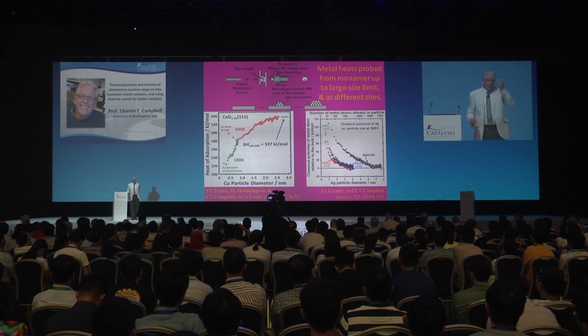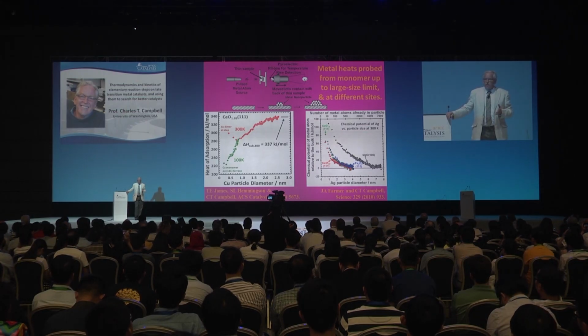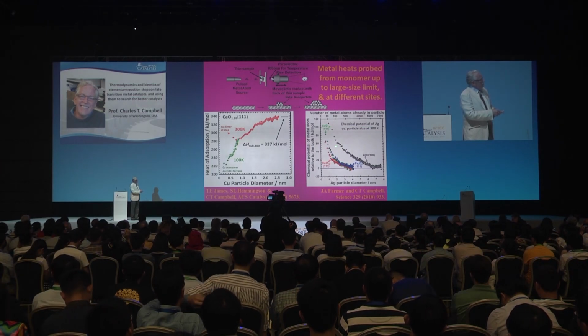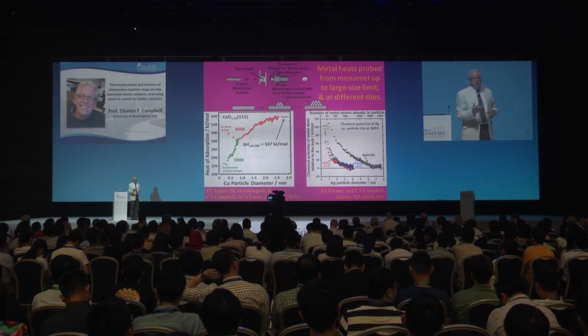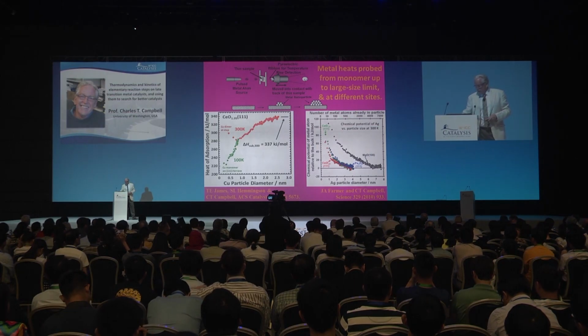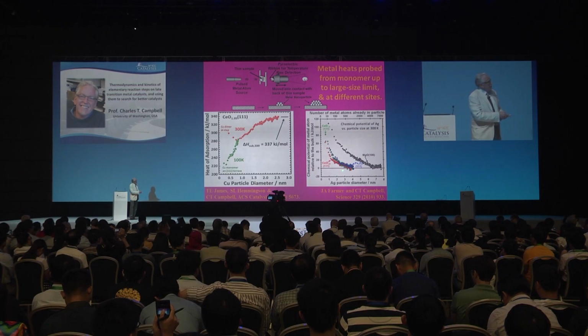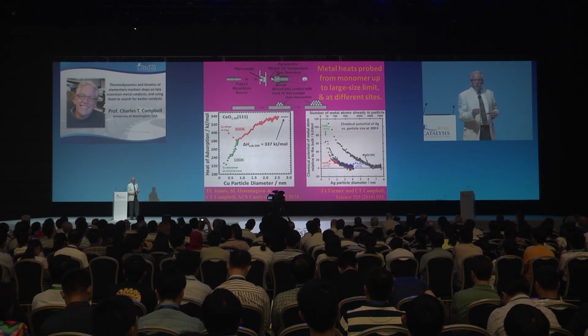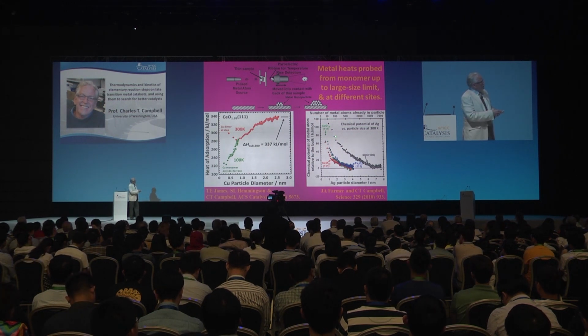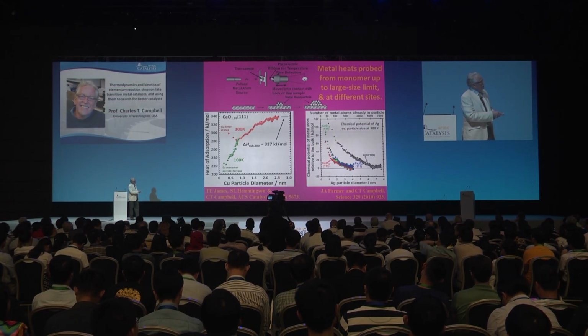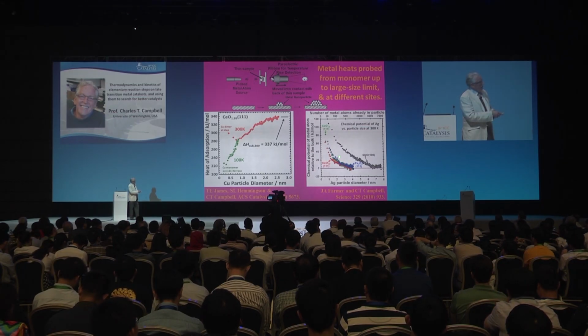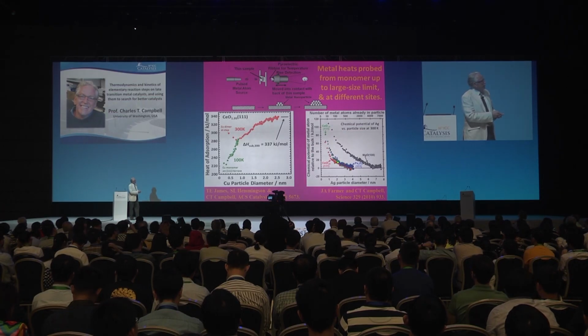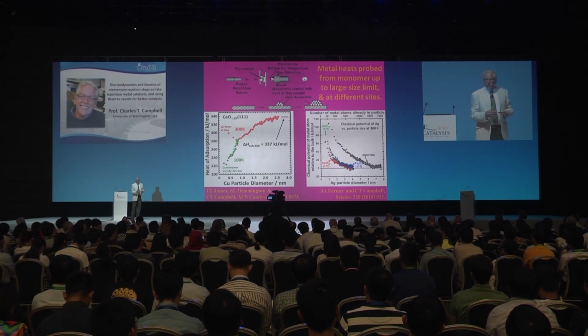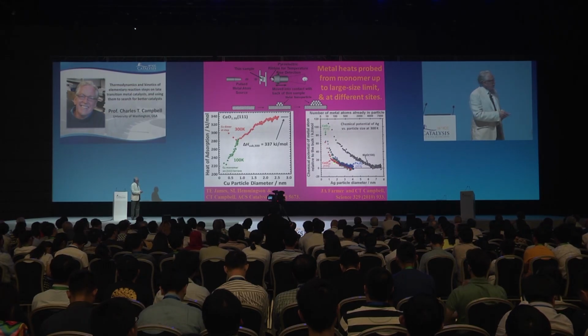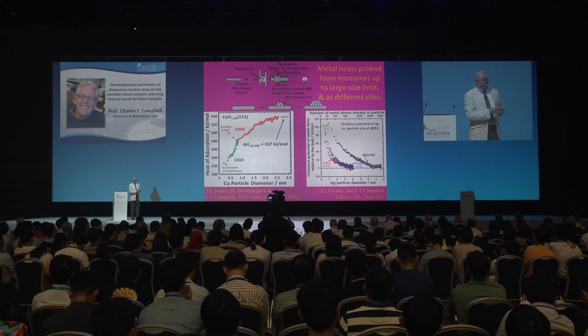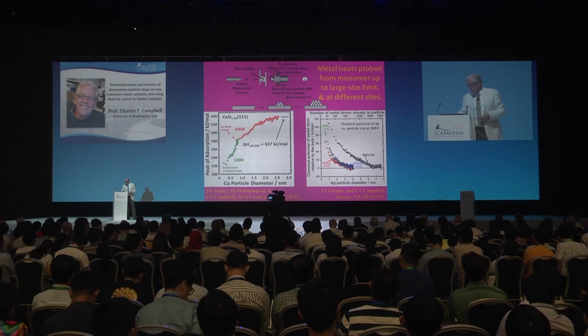So these energetics of metal binding, I think, are crucial to knowing how to go forward in choosing support materials to do what you want to do in catalysis. And crucial to that is knowing how the different support materials control the chemical potential of metal atoms in particles of the same size. Like here, it's clear that silver atoms in 2 nanometer particles are much higher in chemical potential than on these more reducible oxide surfaces by like 60 kilojoules per mole or so. And why is that is the big question. And can we understand the systematics of how one oxide controls to have low chemical potential and another oxide has metal atoms that have high chemical potential for the same particle?